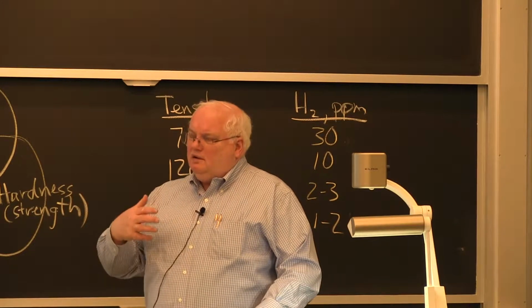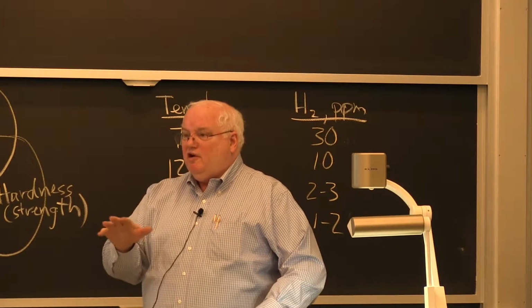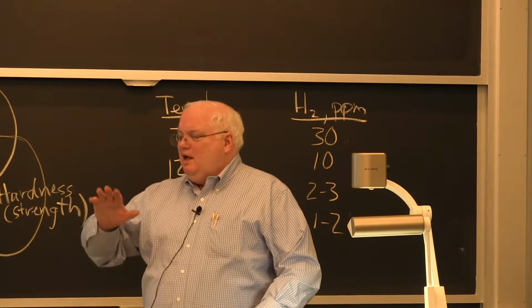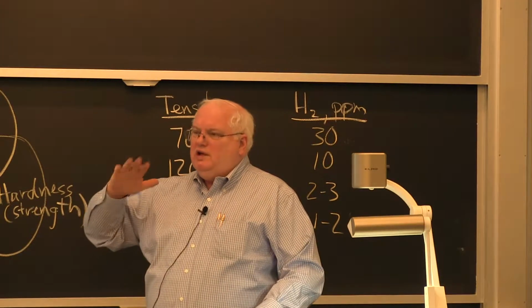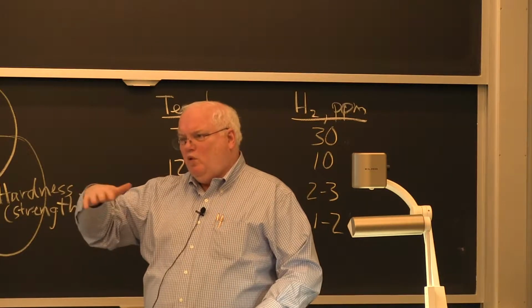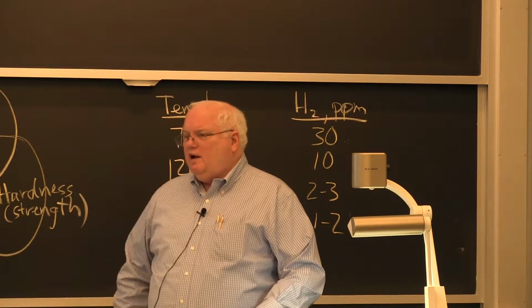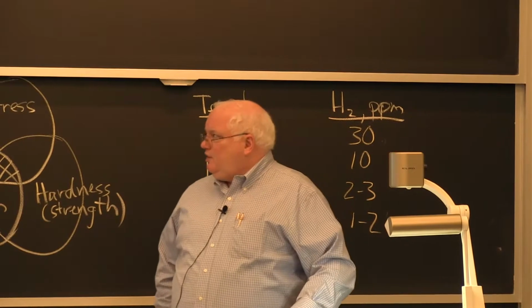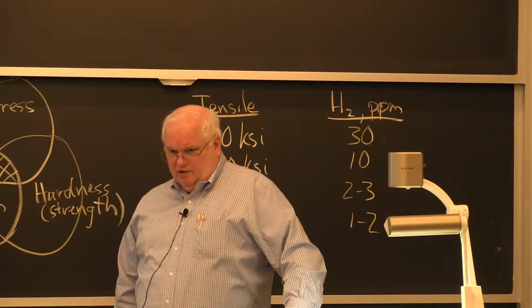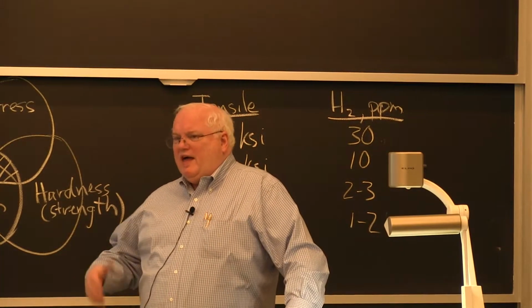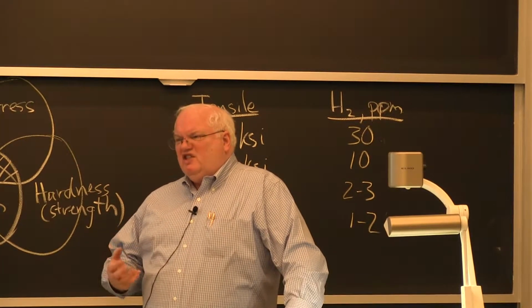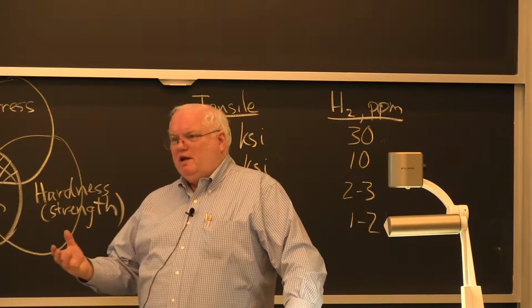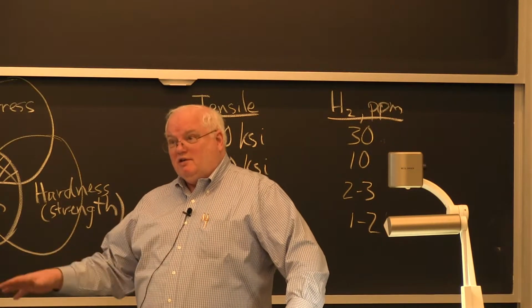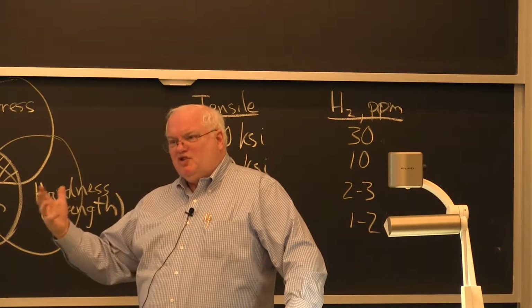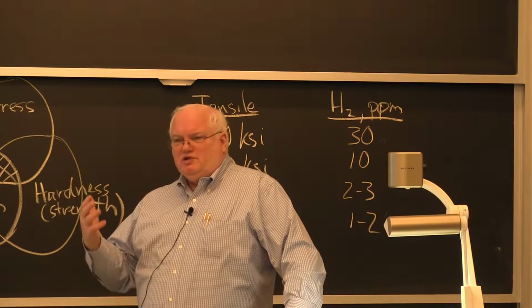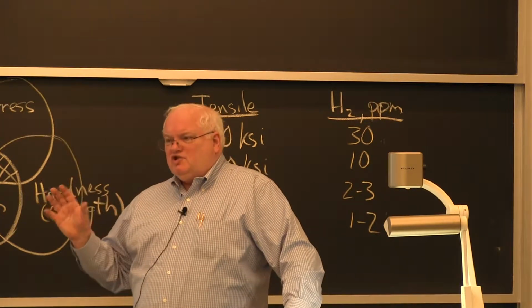Well, the question is, does this 375 cause warping? No. Steel, to start relieve residual stresses or introduce warping in steel, you've got to be above 900 degrees Fahrenheit. Typically, we stress relieve steels in the 1100 to 1200 degree Fahrenheit range. And that's where you're actually starting to see the steel creep like silly putty, if you will. You can't see it creep like silly putty, but it's creeping enough to relieve the strains that are locked in. We talk about residual stresses, they're really locked in strains.